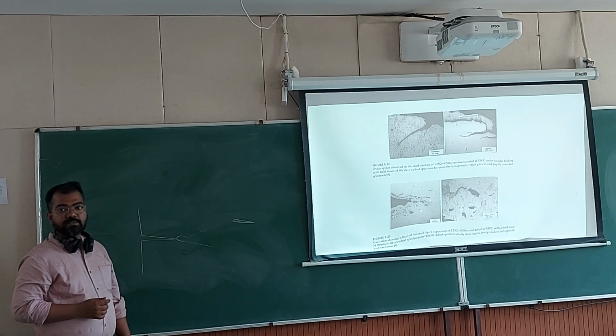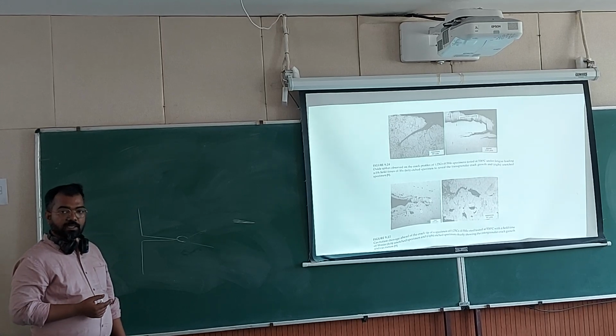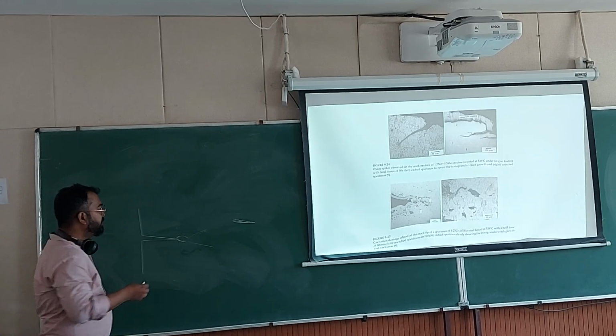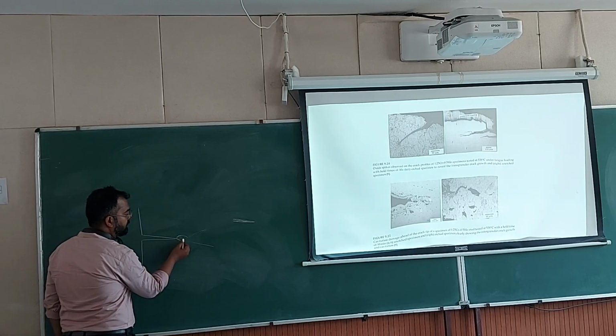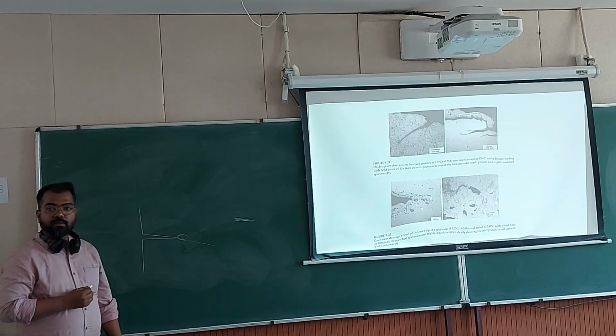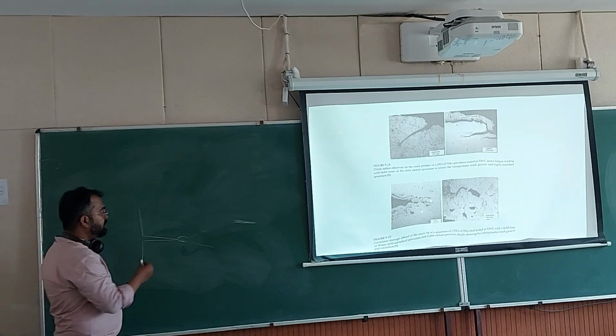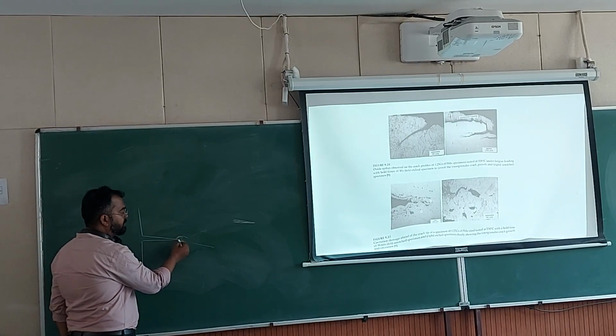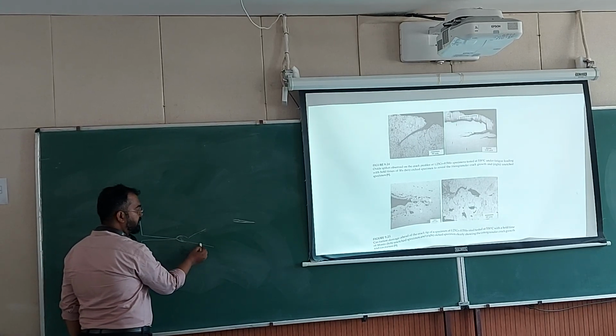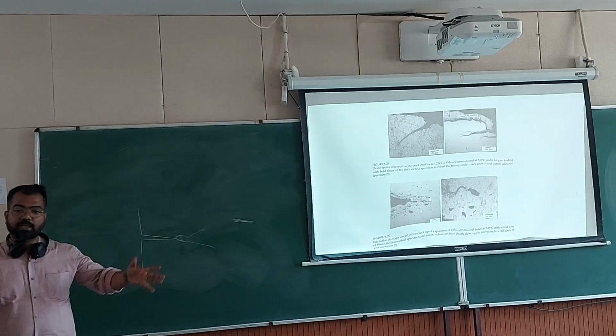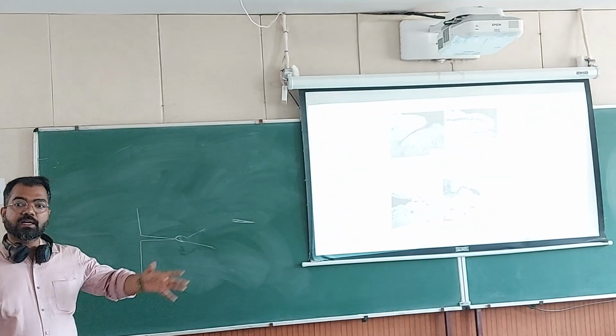So these high stresses will cause more corrosion to happen there, and once corrosion happens, there will be dissolution here. Okay, and so these two will join together and it became something like this, and then in the shear direction again stresses are higher, so again corrosion started happening in that direction.